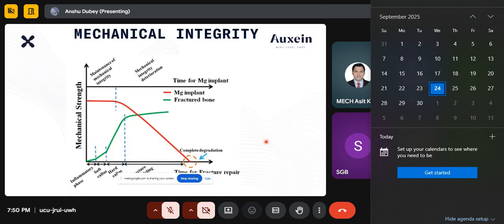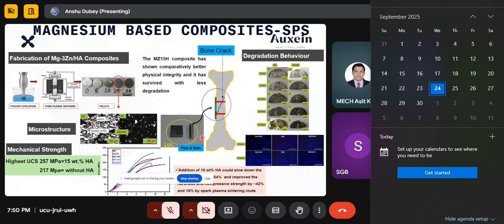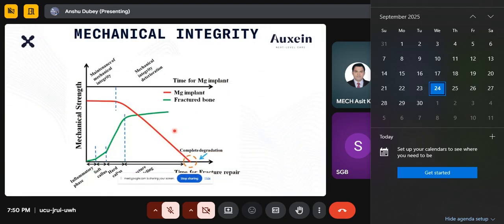The next step, mechanical integrity. Now, after checking that this composite is working fine with 15% of HA, the idea we had in mind was how much strength has been retained after 3 days or 7 days or 14 days. So in this graph which I was talking about previously, the red one is the magnesium implant, and the green one is the fractured bone. So these two graphs should coincide. It should not happen that the magnesium degradation is very fast and the bone has not healed yet. So we need to maintain these two graphs together.